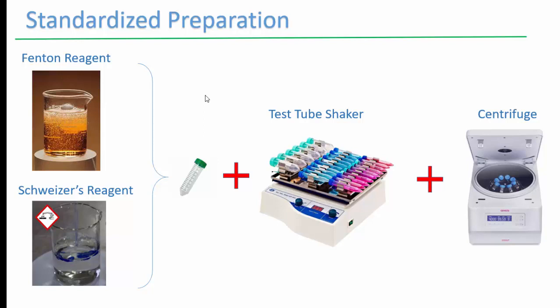And we typically do these, although they're pictured in beakers here on the screen, we typically do all of this within a single conical tube, and that same tube is used throughout. Therefore, there's no transferring of solutions from one beaker to another where you could possibly encounter contamination. Everything's done in a single vial. So you'd add your reagent to the vial, shake it for the time interval, centrifuge it, open the vial, put in your second reagent, shake it, centrifuge it. So we're trying to minimize contamination throughout this process.